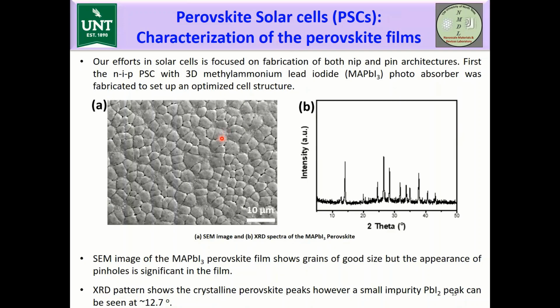To characterize the photoabsorber MAPbI3 layer, we use SEM and XRD. Here in this figure you can see the grain size of the MAPbI3 perovskite is quite good, but the number of pinholes can be evident in the figure, like here, here, and here. And from the XRD, we can see at around 12.67 degree there is a small impurity peak of PbI2. Although the crystalline peaks of perovskites are evident from XRD, there is still a small impurity peak.